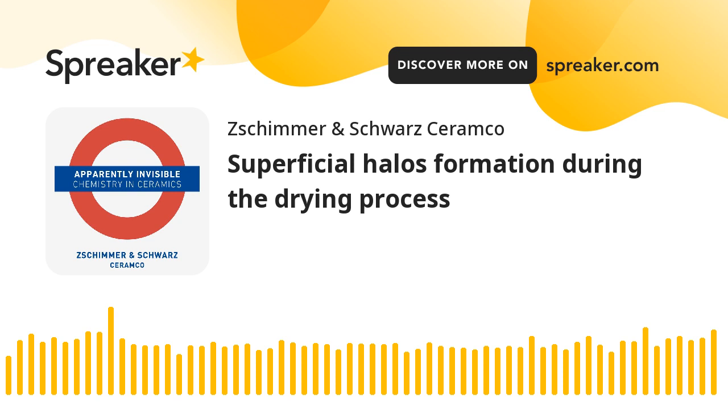So, if this is the scenario, what kind of action can be taken to manage or prevent a problem that, even if it's infrequent, is not as rare as you might think? Okay, firstly, it is necessary to check the timing of the drying cycle as well as the homogeneity of the temperatures and the heat within the dryer. The proper setup of the industrial plant is, in this regard, an important precondition to prevent the issues.